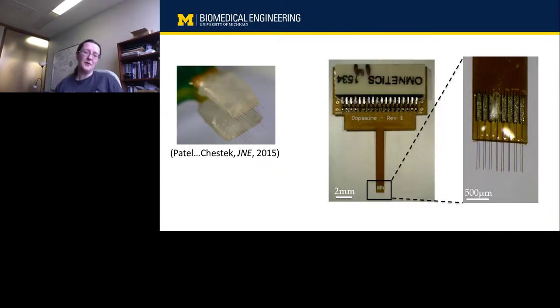All right, so that was one way of making the carbon fibers 500 microns or less. Another way that was really useful in a lot of applications is we put a dissolvable material on the electrodes. So you can see that pictured on the left. And then, you can penetrate the brain with the first part, and then you can melt off the rest of the material as you go.